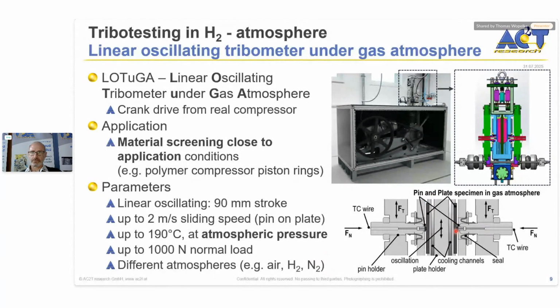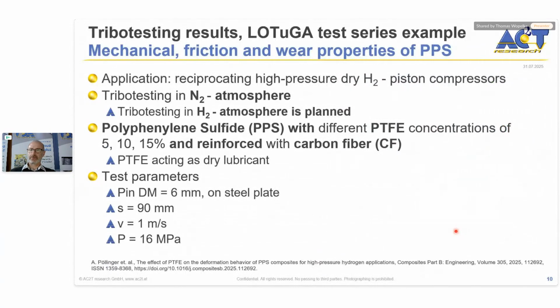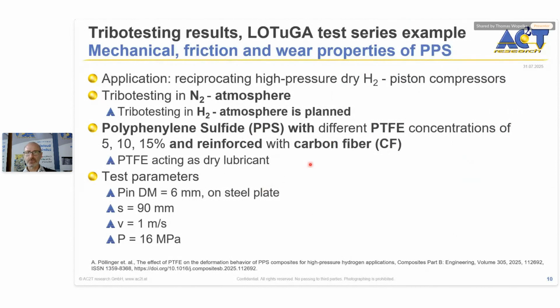I want to give you first results of investigations we did. So the application here was to test materials for high pressure and dry hydrogen piston compressors. I have to mention the first tests were done in nitrogen atmosphere, but testing in hydrogen atmosphere is planned as the next step. We investigated polyphenylene sulfide with different PTFE concentrations, which was reinforced with carbon fiber, which is a candidate material for piston rings in hydrogen compressors.